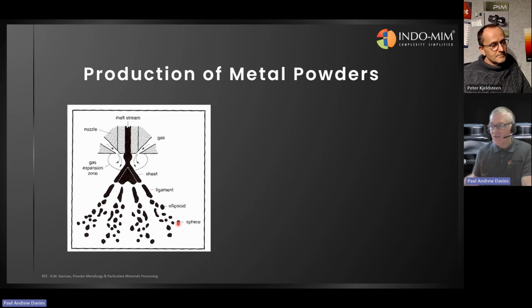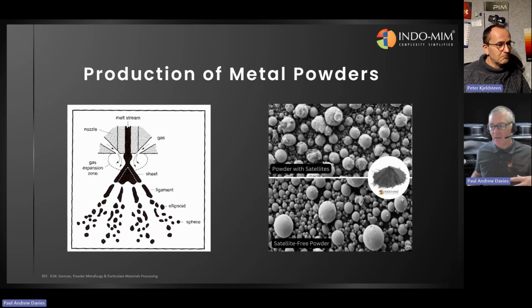Ultimately, it's about the energy efficiency of allowing that molten material to stay molten for secondary atomization, and that's often very important. And of course, if you get your gas to metal flow rates wrong, you can end up with nozzle blocking, because you get a low pressure void beneath the nozzle, and then it can effectively just close off and freeze, and then you have to remove the nozzle, remove the tundish, and start again. Or you can end up with flakes and needles and also satellited particles as well.